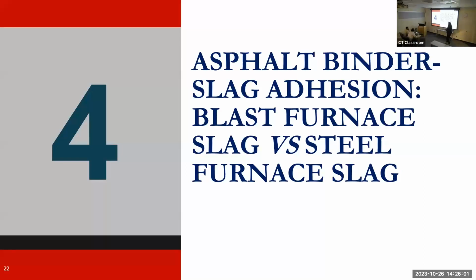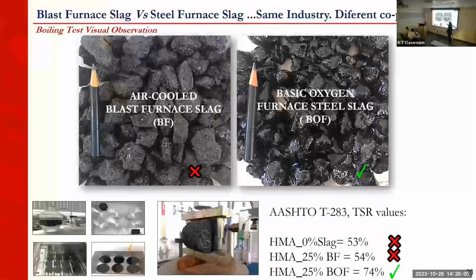In another study, I showed you two other types of slag, BF and BOF. BF showed very poor adhesion to the binder. You can see on this image, it's very clear. Same amount of binder on a different type of slag, you see that good adhesion, right?